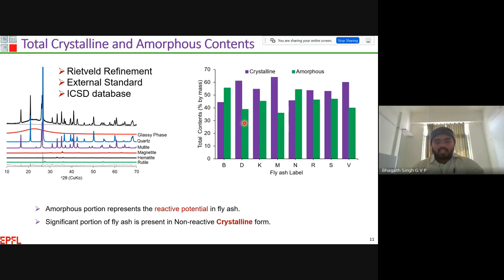And as you can see here, the total crystalline and total amorphous content varies significantly from one source to another. If we compare the sources from B to D, the fly ash B source contains lower crystallinity, whereas fly ash D contains higher crystallinity. If we compare fly ash M and fly ash D, both show more or less similar amorphous content, but if we compare with fly ash B, it shows lower amorphous content.